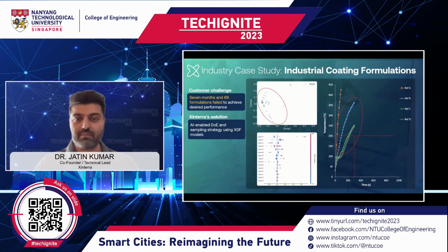So the first thing we did was we took that data, and it was about 12 to 15 parameters of different constituents, the fillers, the surfactants, the base polymers that make up your final formulation. And we compressed that 12 dimensions into 2 dimensions in order to visualize how diverse the different experiments were. And what we found, which is no surprise to us, is that a lot of the experiments were very close to each other when compressed into a 2-dimensional space.